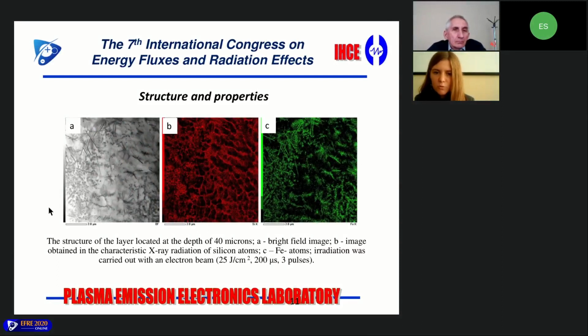It is shown that the structure formed in silicon samples during irradiation with an intense pulsed electron beam depends on the distance from the irradiation surface. And in the layer located at a depth of more than 40 micrometers for 25 joule per square centimeter and 60 micrometers for 40 joule per square centimeter, a structure is observed that forms as a result of partial melting of silumin: aluminum and silicon melt, but needle-shaped iron-based intermetallic inclusions remain, and you can see it here.